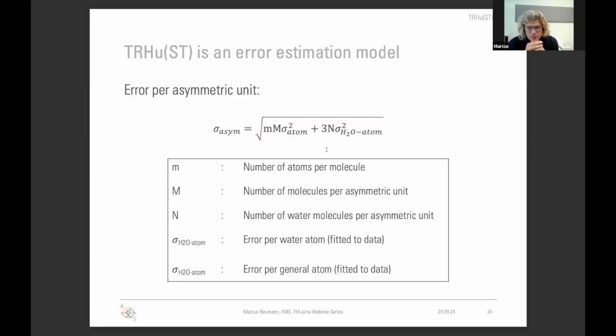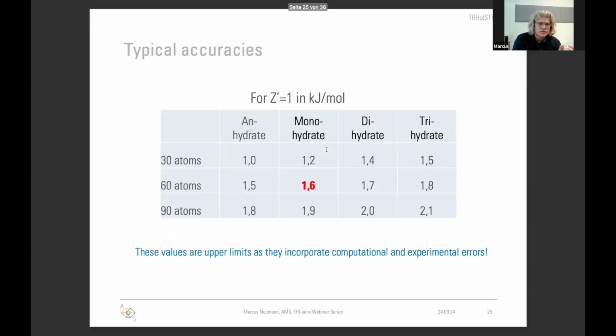Now, you are probably not used to looking at energy errors per atom, so I won't show you the numbers that we got out of the fit. The only thing I show you is this table. And if you want to retain only one number, then that is a 1.6. So at the moment, for a 60-atom compound with one chemical unit per asymmetric unit, so Z prime 1, and a monohydrate, we have an accuracy of 1.6 kilojoule per mole, measured against experiment.